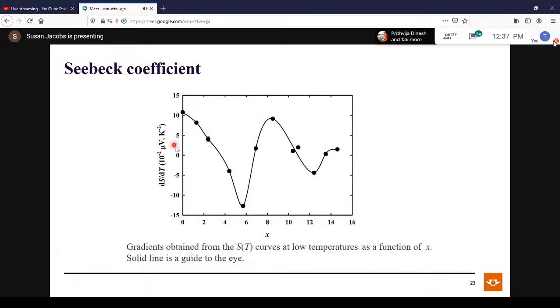Okay, so if we look at the gradient of the Seebeck coefficient at low temperature, we get a trend like this. Once again, from 0, it drops sharply to past 4%, and then there's a sharp increase and steady decrease through the critical concentration, tending to flatten off in the paramagnetic region. So definitely there is something happening here, which we saw in the phase diagram as well. There is something else happening here. So this anomaly we can associate with quantum criticality, but as for this one, we still needed to investigate further.